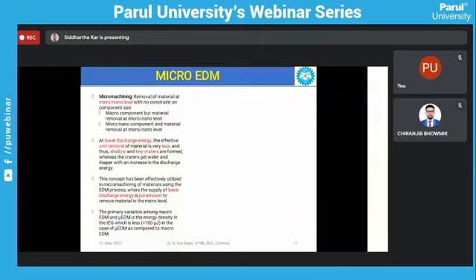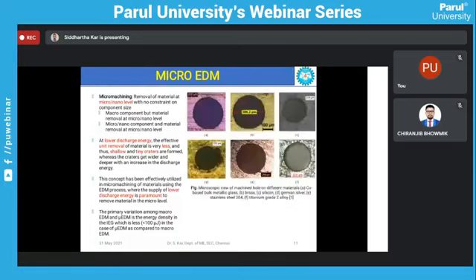The primary variation between macro and micro EDM is that the discharge energy is very less in case of micro EDM. The energy is less than 100 microjoule as compared to macro EDM, where it can reach several hundreds of joules. Now these are a few micro holes drilled on several workpieces, such as copper based bulk metallic glass, brass, silicon, German silver, stainless steel, and titanium grade 2 with the help of micro EDM process. It has been observed that with the increase of discharge energy, the machining time decreases, but the surface quality also deteriorates. So we have to choose the discharge energy according to our requirement. A trade-off has to be maintained.